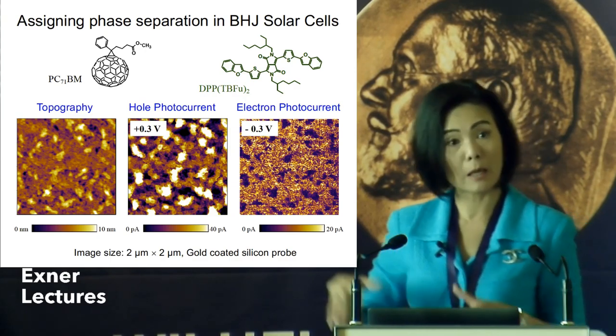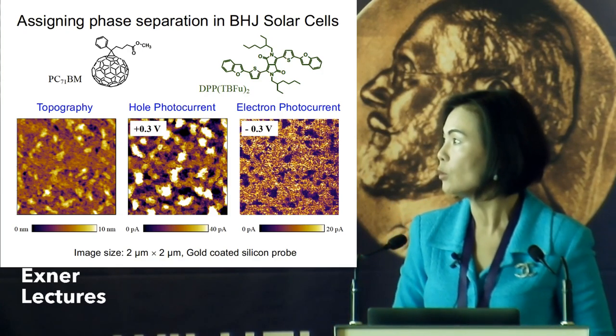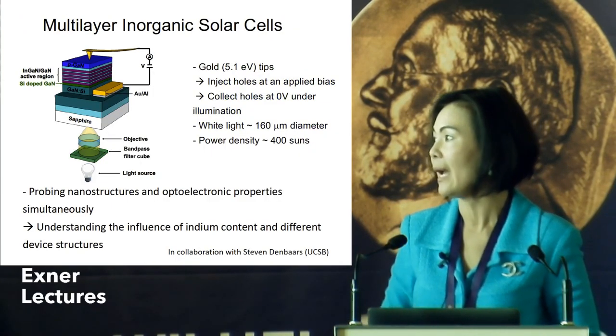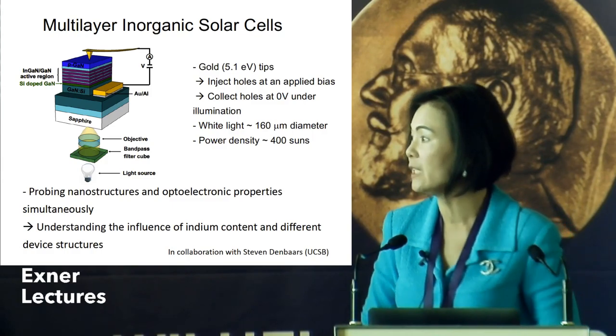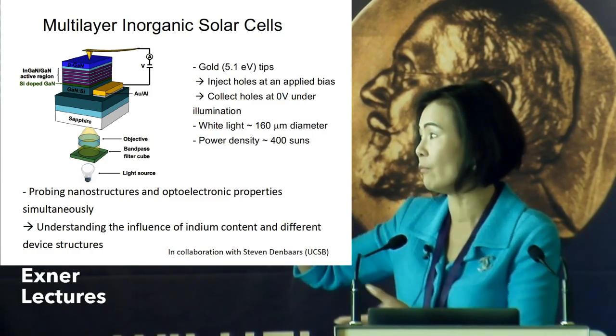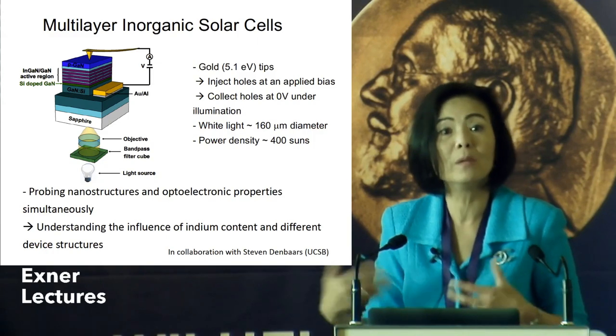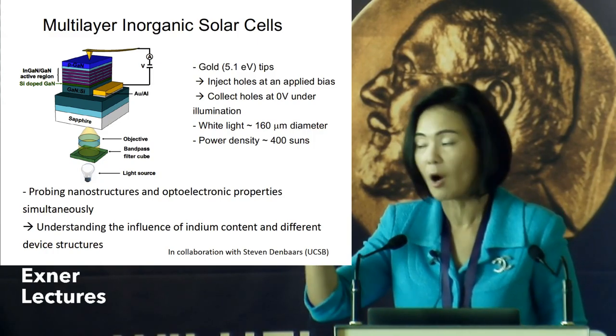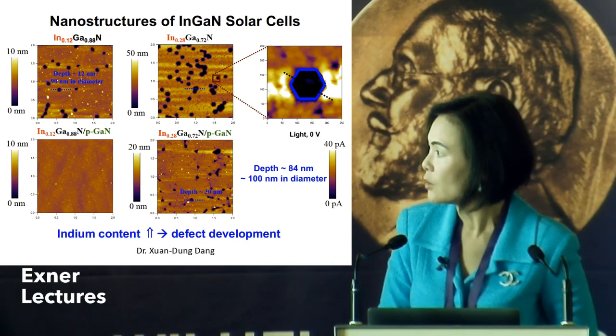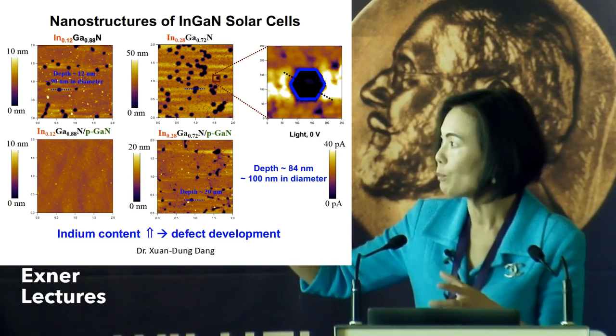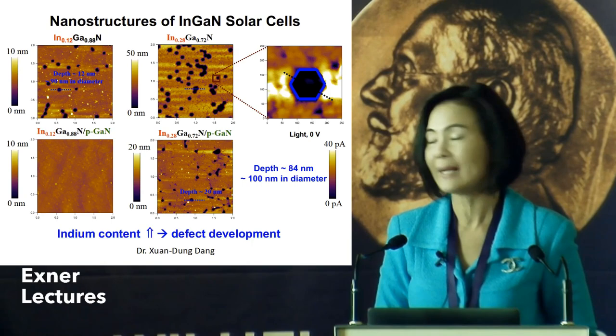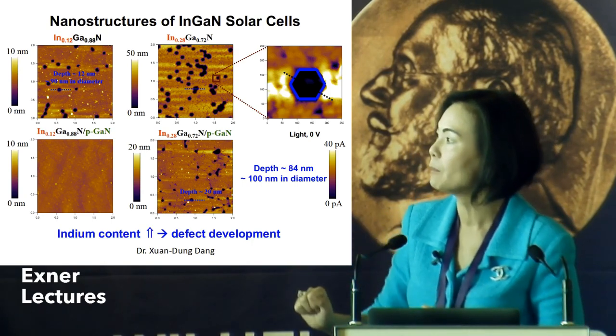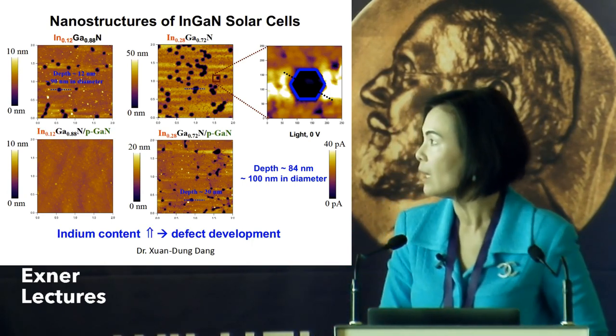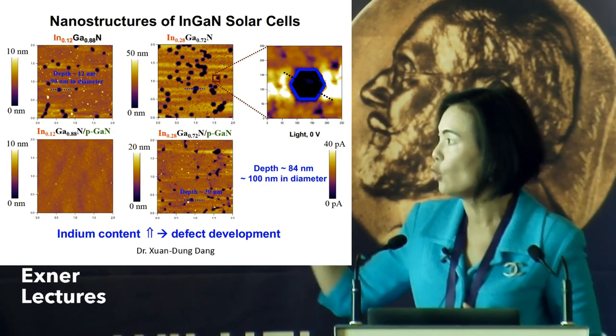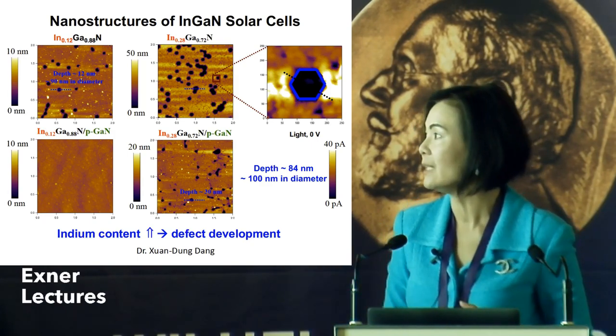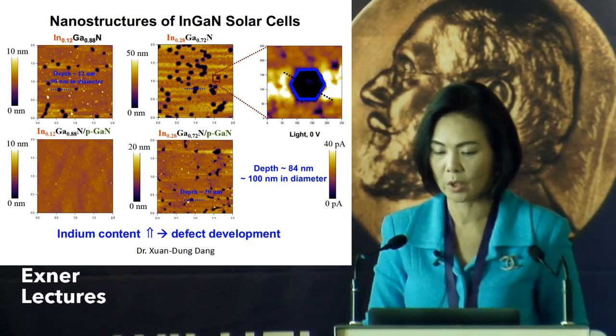And so we can apply the tool and look at a multi-layer inorganic solar cell. This is in collaboration with UCSB because they have this stack of solar cell. It's very challenging to know, if the device doesn't work well, what causes that. So here they actually have different doping levels, indium doping, and if you have higher indium content, you see the defect, the hole, and we are able to go in and look at those defects, and you can see that in the defect, you don't see the photocurrent.